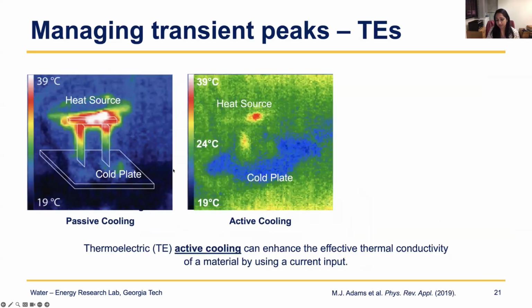We also do something with thermoelectrics, but we're using thermoelectrics very differently. So typically, you have your heat source here and a cold plate on the bottom, and you have your thermoelectric material, so a P-type and an N-type semiconductor connected like this. So this is the thermoelectric in the off state. And so it's off, meaning that there's no current being supplied to the thermoelectric. So we have the heat source at almost 39 degrees Celsius and the cold plate at almost 20 degrees Celsius.